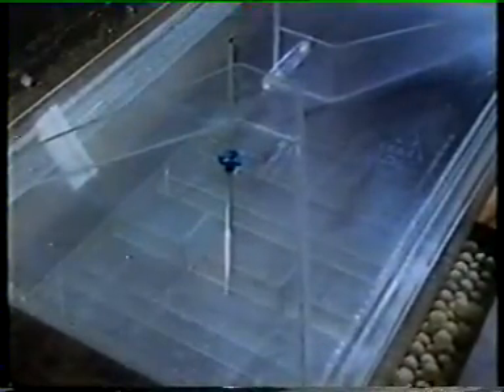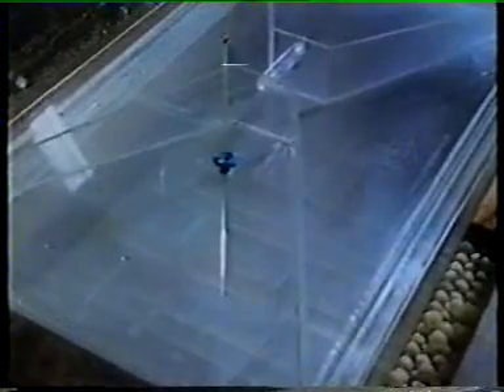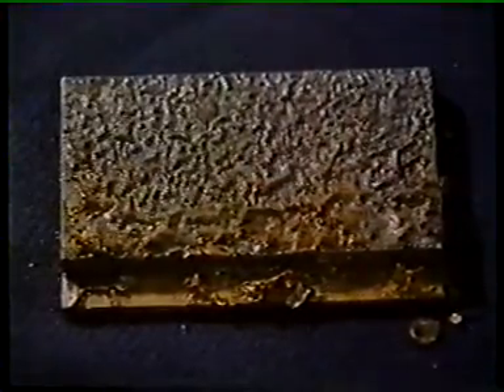These samples of mild steel, copper and aluminium have been put into a heavily corrosive atmosphere which accelerates the normal processes of corrosion. When the samples are removed after a few hours, the non-ferrous metals have corroded slightly. In the case of aluminium, the oxide formed provides a protective coating. But the mild steel is very badly rusted.